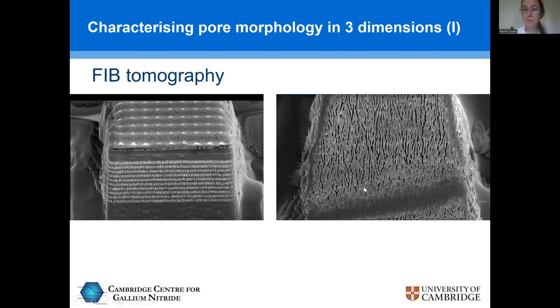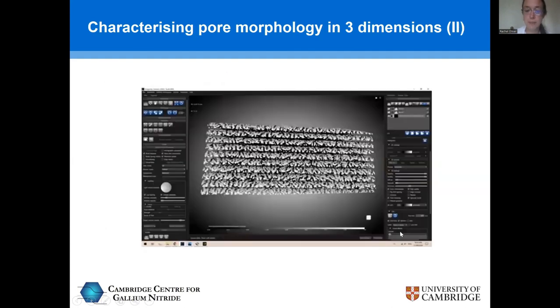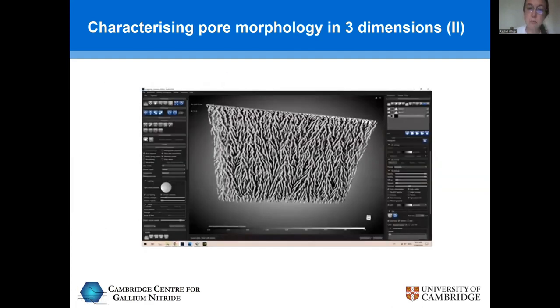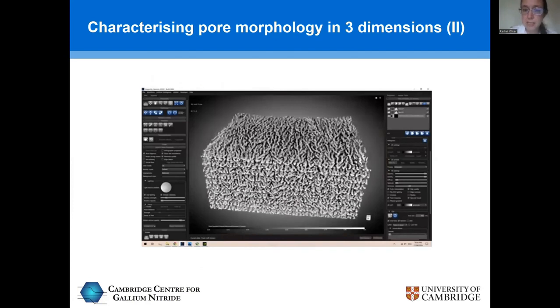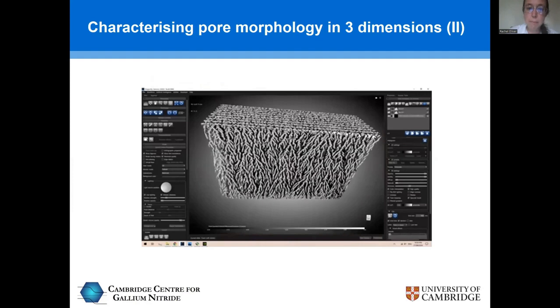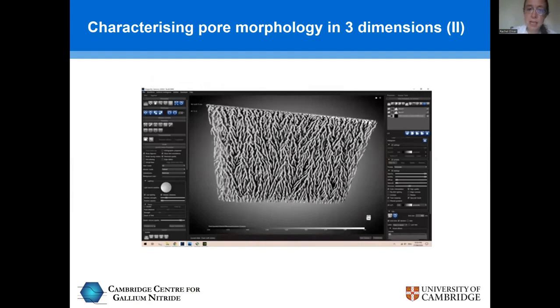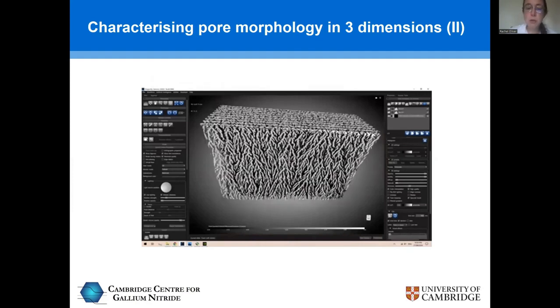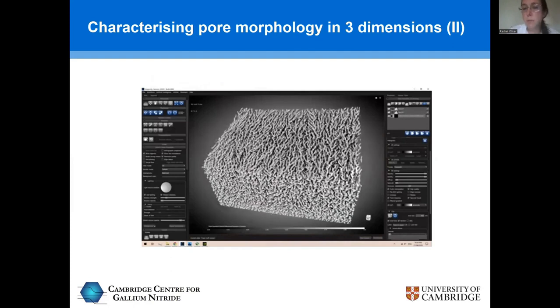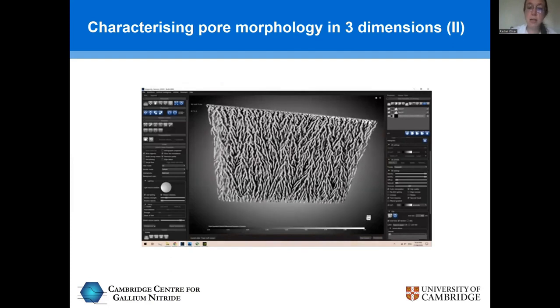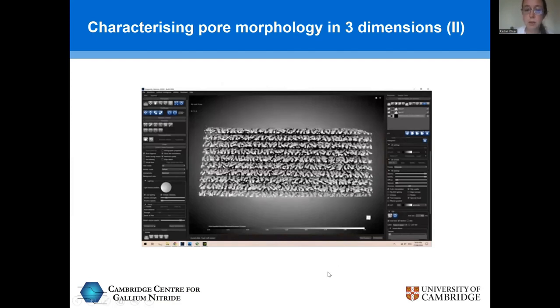And we can see we don't have the perfect aligned cylindrical pores of the model, but we do have a very strong preference for alignment of the pores in a particular direction. And this is the kind of full three-dimensional reconstruction of that data. You can see these multiple slightly branching porous layers, and we can extract any one of them, and they're all branched but with a predominant direction in which the porosity lies. And that's what's leading to the birefringence that we see, that anisotropy of the porosity.